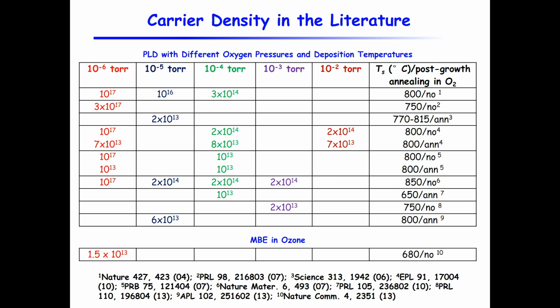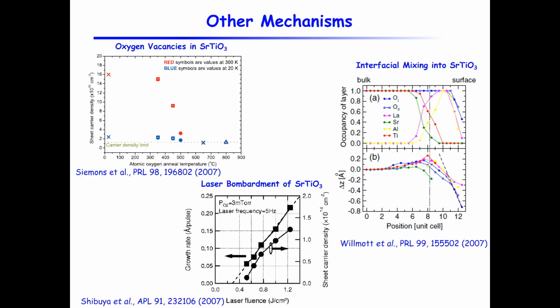And there are other papers from the group that show that it is actually very much random. So that's, I believe, something not many people talk about. But of course there are theories to explain why they have this not consistent with the prediction. And of course, partly due to that, and also just from the skepticism of the whole thing altogether, there are other mechanisms that have been proposed, like oxygen vacancies in strontium titanate and bombardment of strontium titanate.